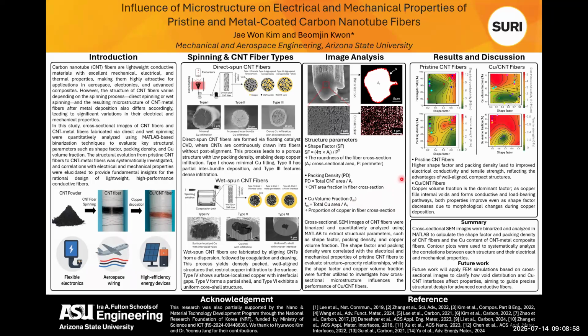Now, I will explain how these structural parameters relate to fiber performance. In the contour plot for pristine CNT fibers, high shape factor and high packing density are associated with increased electrical conductivity and tensile strength. In particular, when the shape factor exceeds 0.7 and packing density was above 95%, conductivity reached 12 million Siemens per meter, and tensile strength exceeded 4 gigapascal.